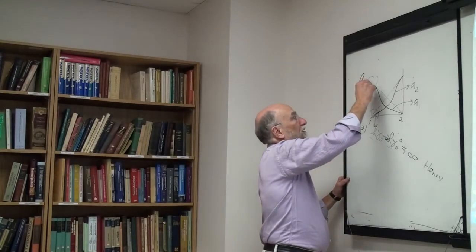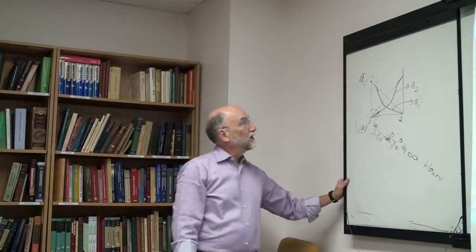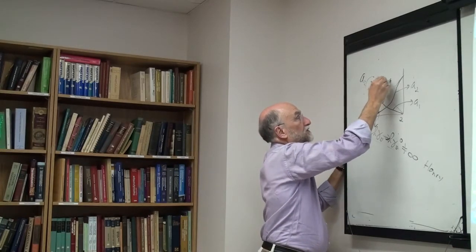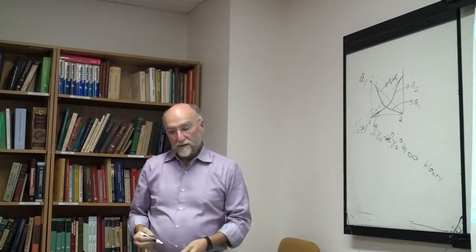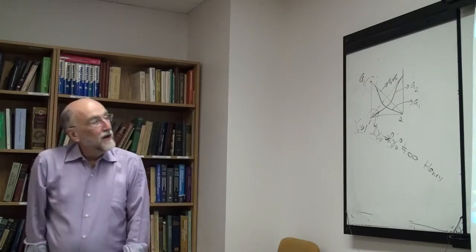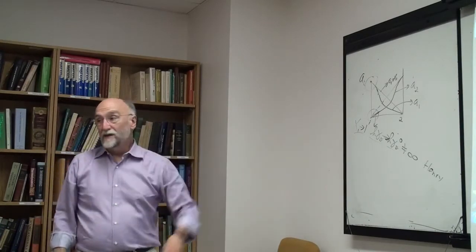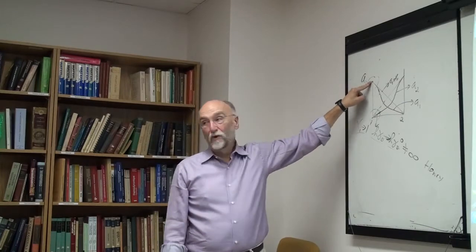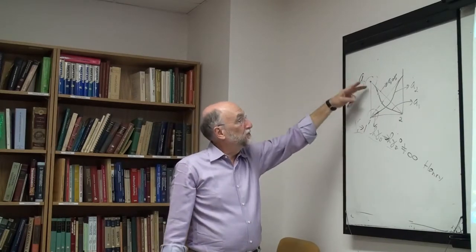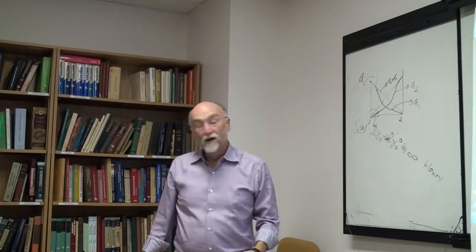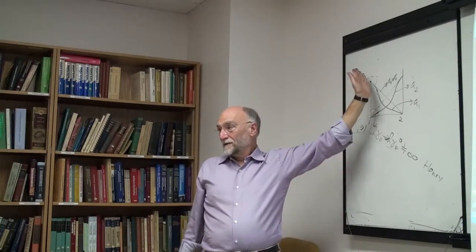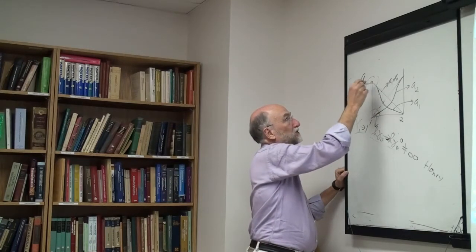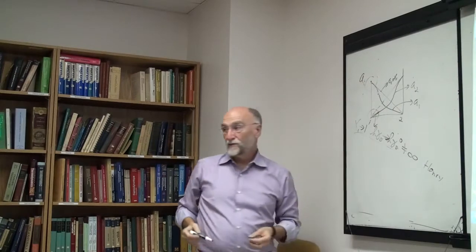And up here we have Raoult's law. Along this line, this is Raoult's line, the activity of 1 equals x1. Now you'll sometimes see Raoult's law listed as: when x1 approaches 1, the activity equals the mole fraction. But certainly when the mole fraction equals 1, the activity has to equal the mole fraction simply by definition, not by any law. Pure component 1 by definition is the point where the activity equals 1. Raoult's law says the slope comes in. This line for activity 1 must go through that point by definition. Raoult's law says it has to come in asymptotically to this Raoult's law line.